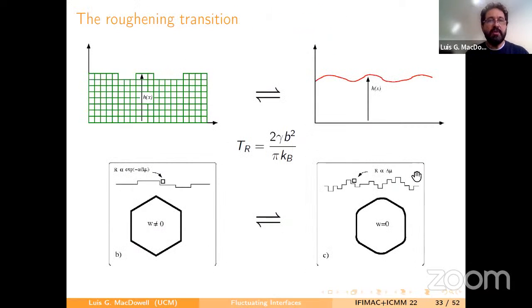Okay, so as far as the interfaces are concerned, what we mean is that there is a transition from the classical picture of a high energy solid with terraces and steps into an interface which is just fluid-like. This is still the bulk solid phase, but the interface will behave fluid-like. And so why should we care about this? It's very important because this is going to change completely the way crystals grow.